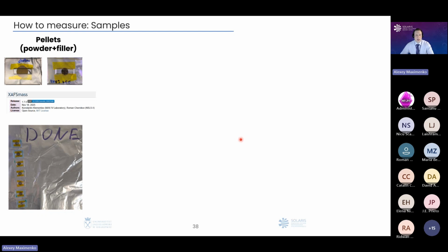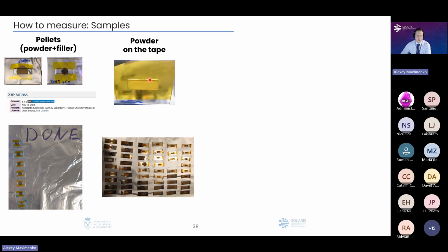And in principle, when we say what kind of a sample we could measure during our experiment, in most of the cases, we say that powders, it is most easy for us to do. We just make pellets from these samples. We calculate what kind of amount of material you need to use to prepare such kind of pellets, and you're going to the synchrotron, and for example here you could see a photo how many samples people could measure in a few hours. Then for example you could put your powder sample on the tape, and then another example how it looks like.